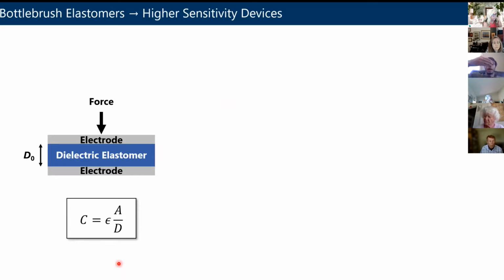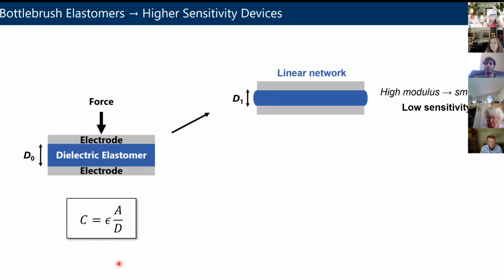Now, if you look at this device in cross section, this is just picturing it differently with a focus on the dielectric elastomer layer. And as you probably gathered, we're going to try to use our new Supersoft materials that rely on polymer architecture to control the stiffness. And if you were to do this with a linear network, you apply some force, you squeeze that material down, well, it won't be that soft. It might deform a little bit, but not a ton. Relatively low sensitivity for a pressure sensor.